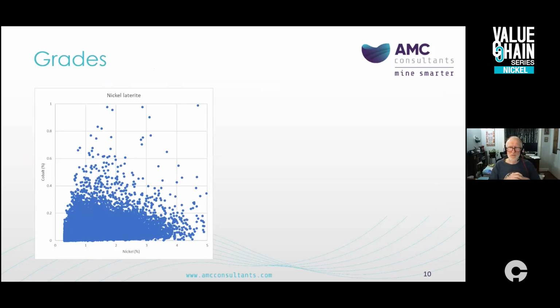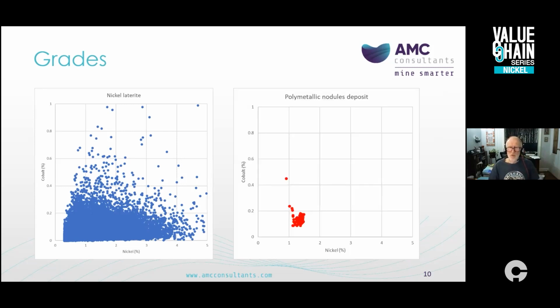Turning now to the grade of nodules. We've already seen how phenomenally extensive the polymetallic nodule deposits are. Another truly remarkable characteristic of the nodule deposits in the CCZ is the low variation in metals grades. To provide a comparison, here is a plot of nickel and cobalt grades within a fairly typical nickel laterite deposit. The samples come from an area of perhaps 20 square kilometers, and we can see a wide spread of grades of both elements. The plot on the right is a similarly scaled plot of nickel and cobalt grades from the NORI-D area in the CCZ, which covers an area of approximately 25,000 square kilometers. We can see that the range of grades is very low and the data points form a tight bullseye. The very low variance means that estimation of grades in this style of deposit is very low risk.